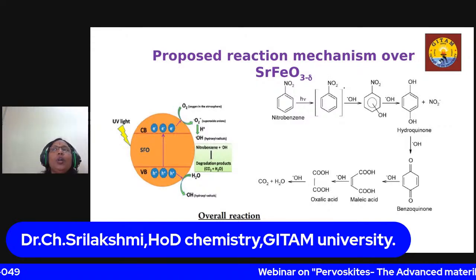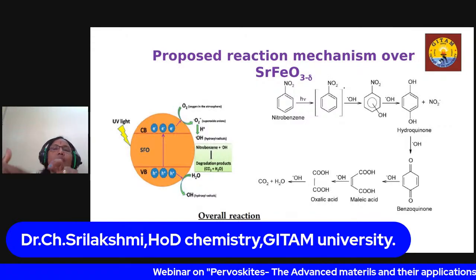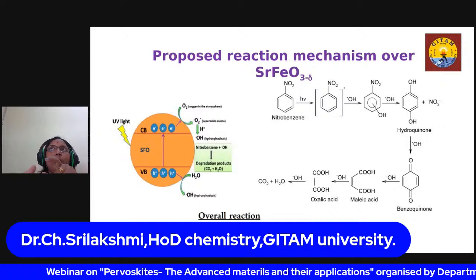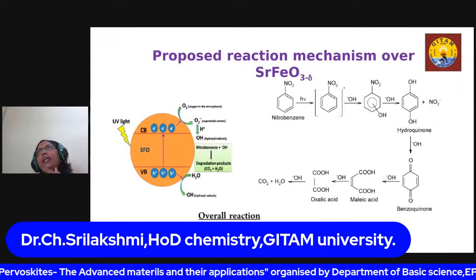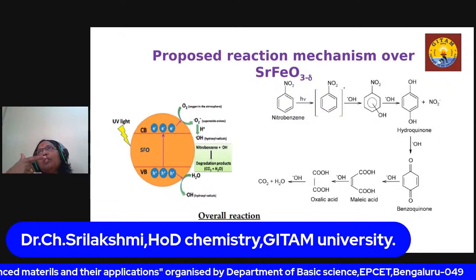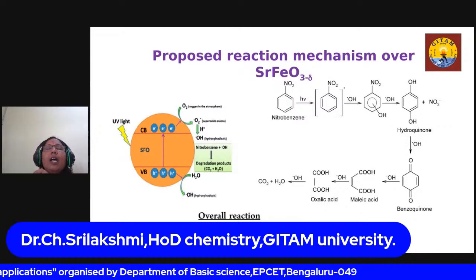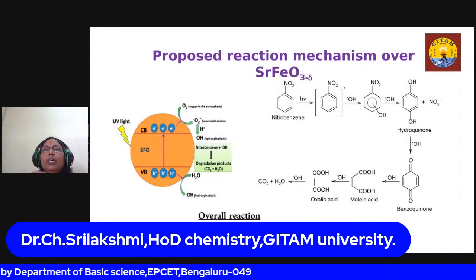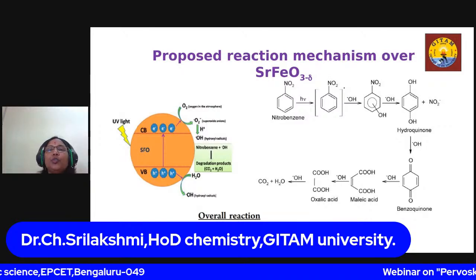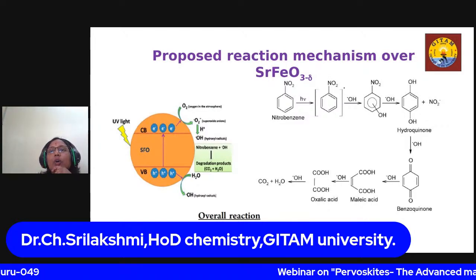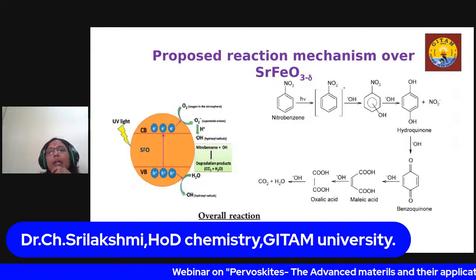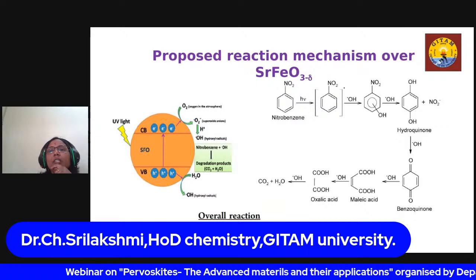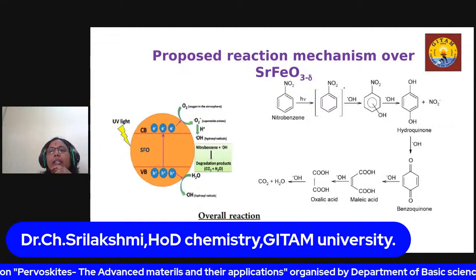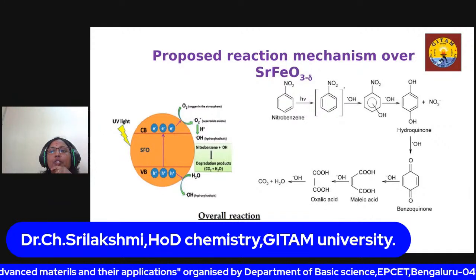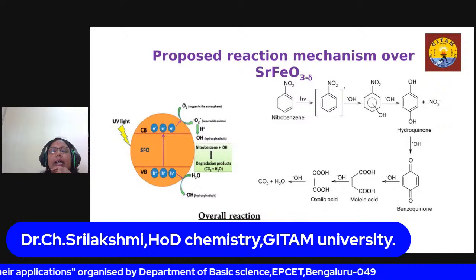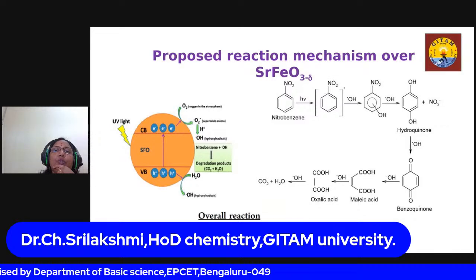That CO2 is interacting with the hydroxyls and forming bicarbonate, and bicarbonate is converting into carbonate, and carbonate is getting reabsorbed on the catalyst surface. That's why degradation is very low over the catalyst where we have used H2O2 as the oxidizing agent. And we proposed this reaction mechanism. Nitrobenzene upon interaction with OH radicals first converts into hydroquinone, then benzoquinone, then maleic acid, oxalic acid, and finally CO2 and water.